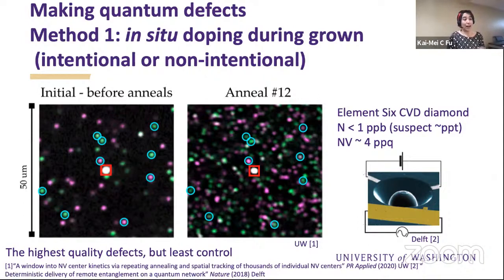So how pure do you need to be? When you start having defect interactions where one charges and uncharges, for example, it's nice if it's hundreds of nanometers away. Basically, that's kind of a nice rule of thumb. Similarly, it's nice if it's hundreds of nanometers if you have the super sensitive long coherence times that you want, for dealing with dipolar interactions that broaden the ground state spins. Okay, and these are very high purities for material growth.